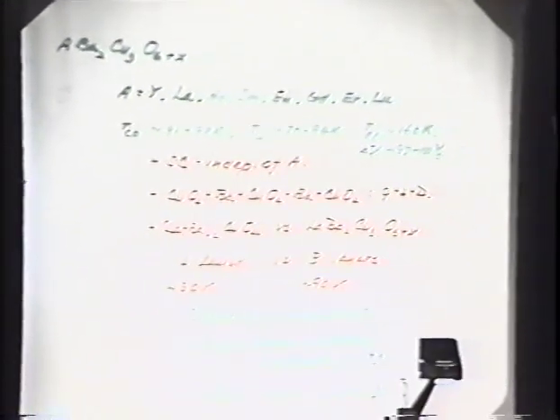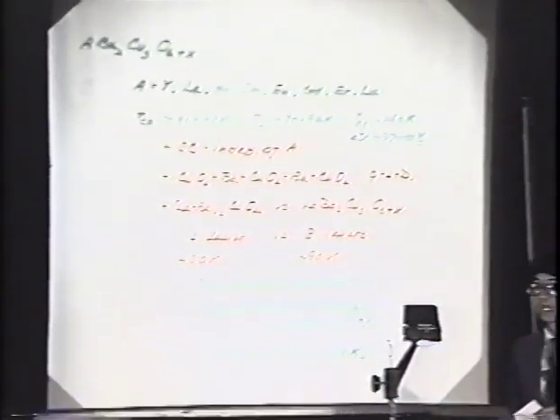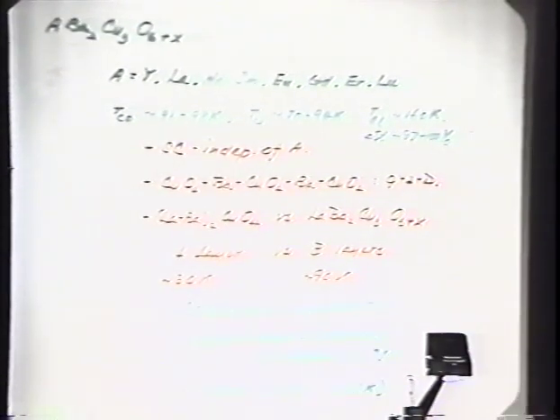Now, with all that, we decided to find out what are the active components for superconductivity above 90 degrees in this class of material. So we decided to replace all these A elements by a whole bunch of elements, and we found that basically the TC is almost constant. Here's the table of all the TC. The onset temperature is between 91 and 98 degrees, and the resistance goes to 0 between 70 and 94 degrees. I believe the 70 degrees can be improved later.